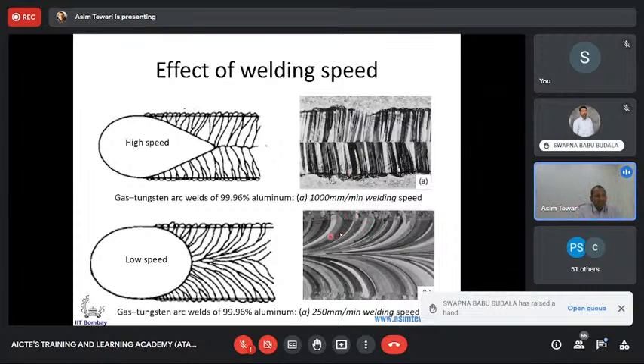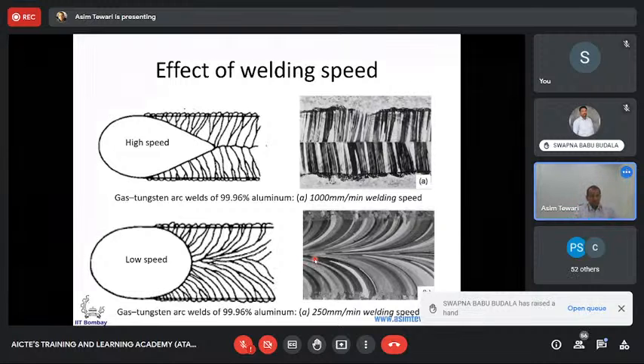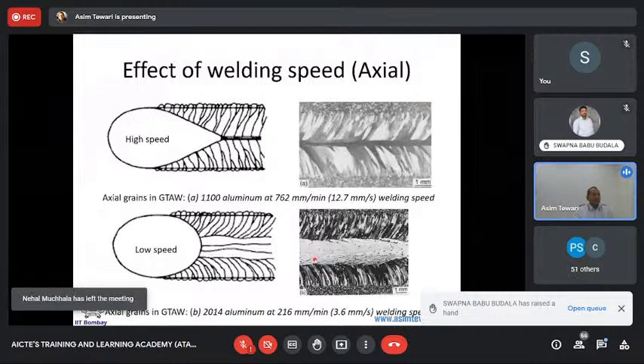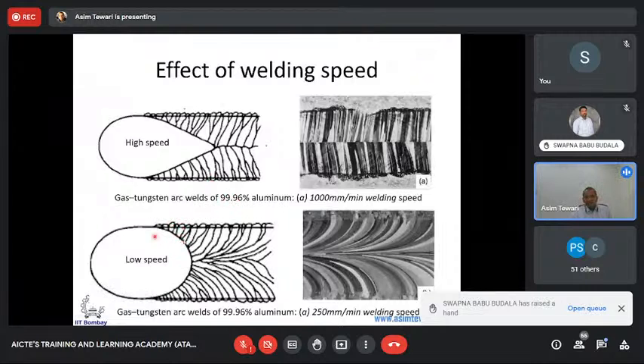Now if you see, this is telling you what the individual grains are and why the grains are growing like this. The grains are growing like this based on the competitive growth between thermal gradients and the orientation. And this could be the other aspect: this is for almost a pure metal. For a pure metal, there is only a single phase, so it's a liquid and a solid, and liquid and solid have almost no gap. Whereas for an alloy, there is a gap, a melting region, right? Which is where it is both liquid and solid, which is the mushy zone. So the solidus and the liquidus temperatures are different.